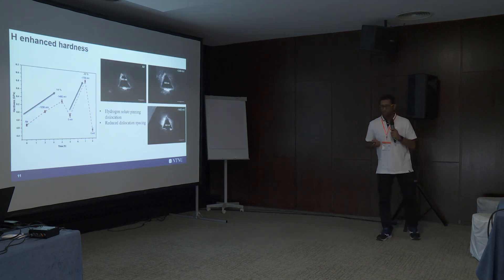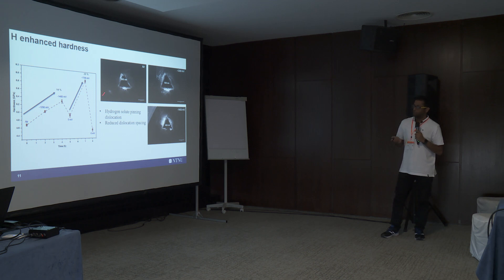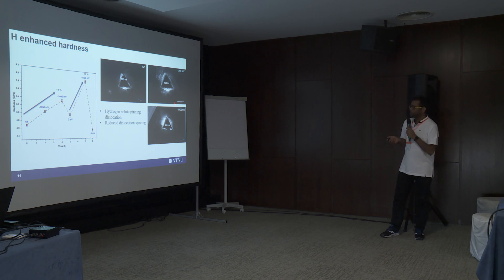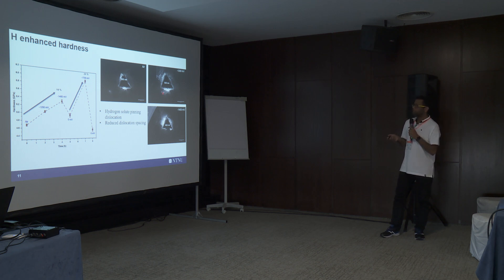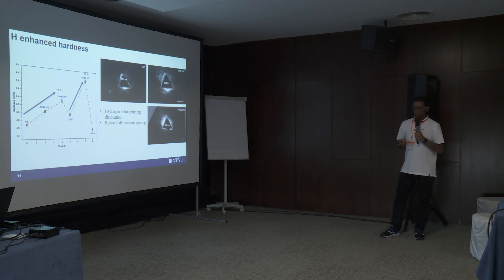Regarding the hardness increase, there is a progressive increase in hardness with cathodic potential, which can be directly correlated with hydrogen content. From the ECCI images, measuring the average dislocation spacing shows a progressive reduction in dislocation spacing with hydrogen charging. The dominant mechanism for the hardness increase is hydrogen solute pinning of dislocations.